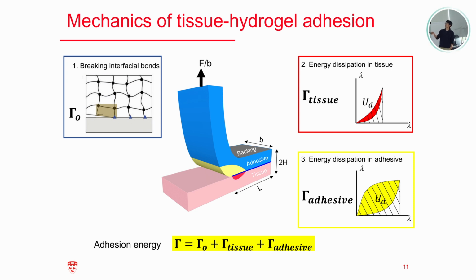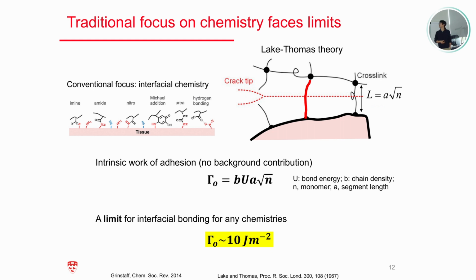In addition to that, you also need to do the mechanical work to mechanically damage the adhesive and the tissue, which is inevitable when you peel this material off. That goes to the energy gamma of the tissue substrate and also the energy dissipation in the adhesive matrix. Together, those make up the adhesion energy of the adhesive. Let's visit them one by one.